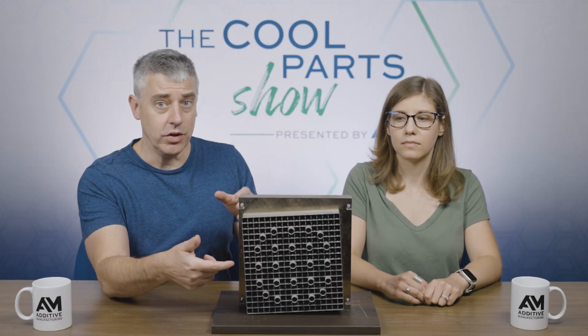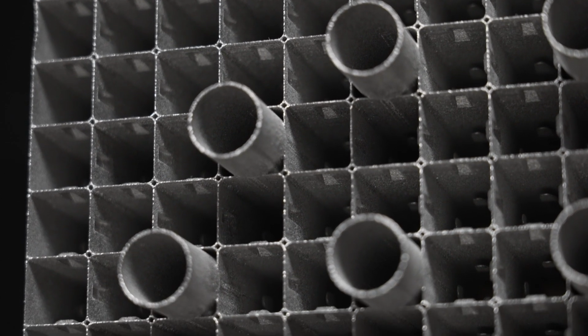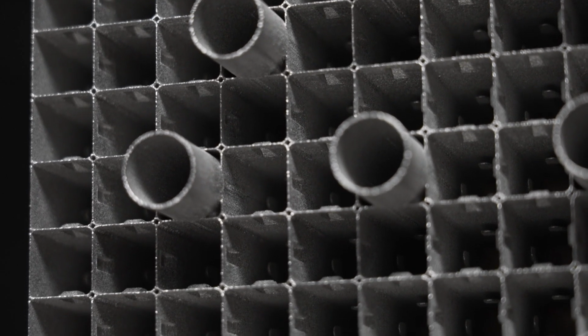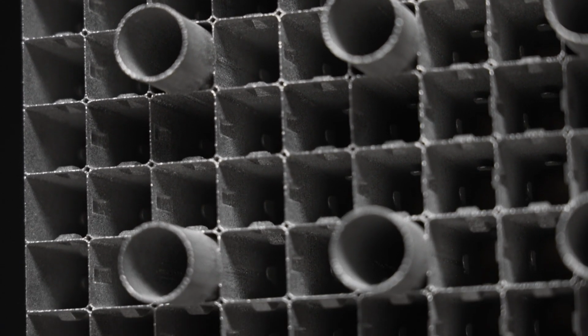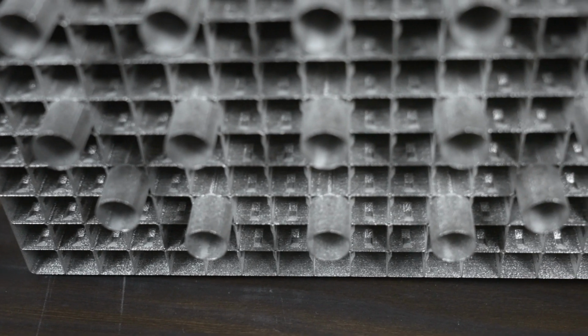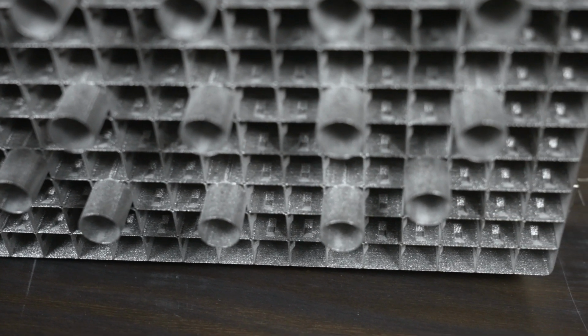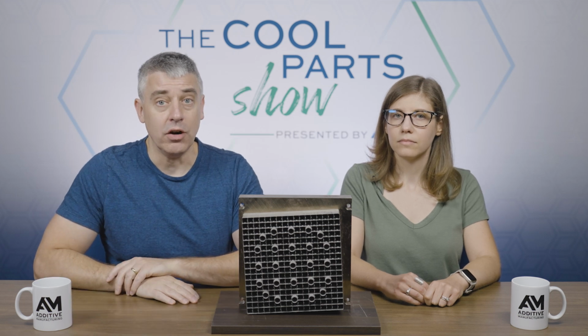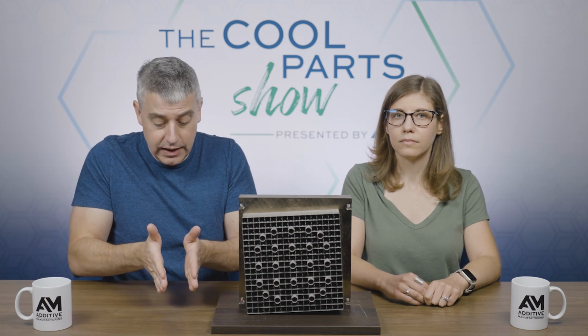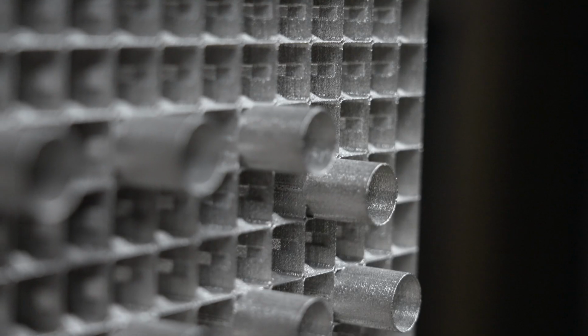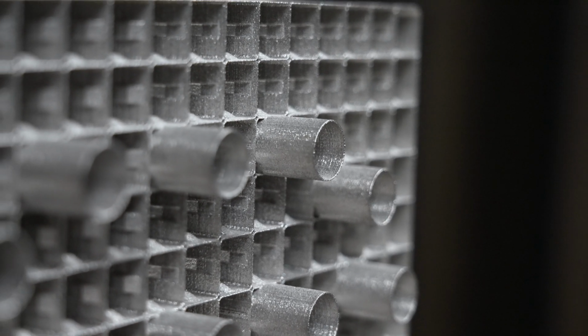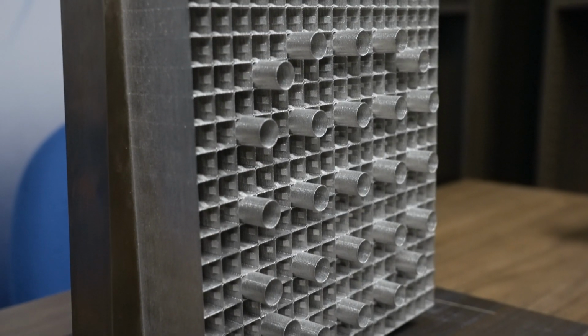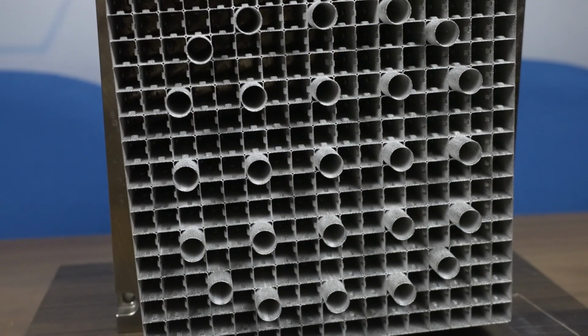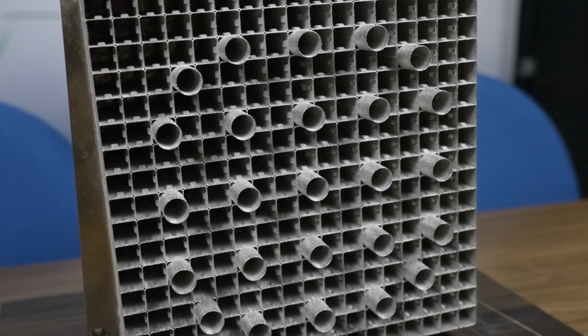So let's talk about these thin walls. Each wall is 250 micron thick, a quarter of a millimeter thick. And the walls have to be very straight and very square with one another. Otherwise, the fuel rods would locate in the wrong place. And that requirement actually influenced the material choice. An easier nickel-based material to 3D print with potentially would have been a different alloy, Inconel 625, but using that metal would have entailed a heat treating step. And there was some concern that maybe the form and dimensions and straightness of these walls could shift a little in heat treat.